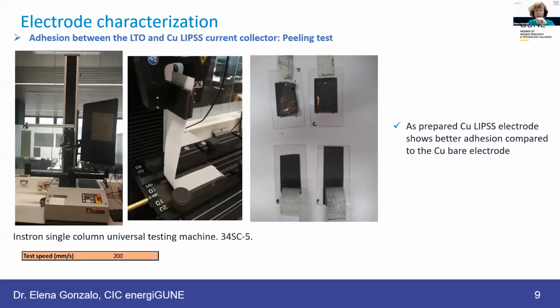One more test that we did was the peeling test, because we wanted to compare the adhesion that we got with our copper LIPSS current collector and with the bare copper foil that we have in the lab, the one that we normally use. To do that, we use this Instron single column universal testing machine. And here you can see some pictures of two electrodes that were cast on bare copper foil and two electrodes on copper LIPSS current collector.